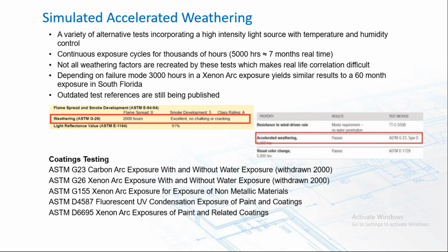But not all failure modes are replicated using these simulated accelerated weathering tests. And some of these weathering tests are more aggressive than others. Some are simply a UV light bulb. Others are the xenon arc weatherometers. But sadly, things do change, and sadly, some of our competition are caught out with these changing requirements. Although you can see here, they're still publishing this data even today, 20 years after the ASTM standard has been withdrawn, as accurate and current information on the performance of their product. So something to be a little bit aware of, because certainly those two ASTM tests have been replaced.